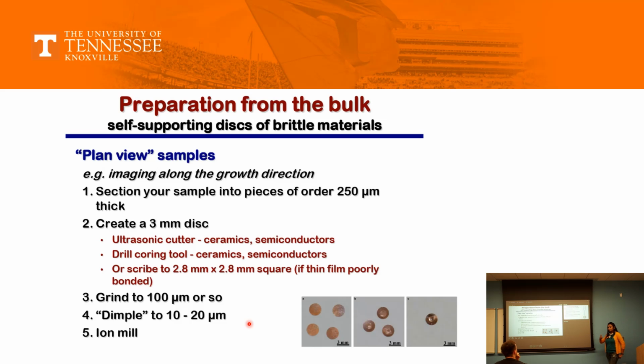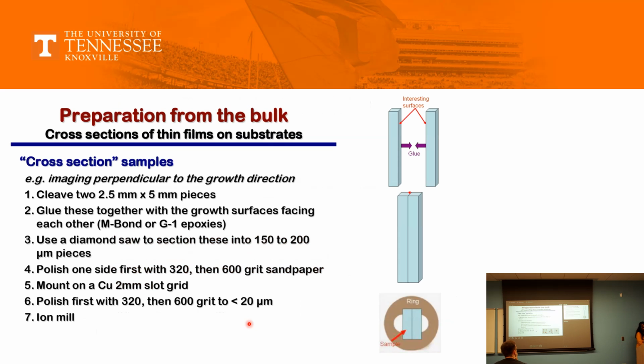When you go to FIB, you will see some samples will take you 8 hours to finish. Some of the intermetallics took that long because they were zirconium based. Depending upon the material, the FIB becomes efficient or inefficient. So now for ceramics, what do we do? All these things were developed initially and were really interesting. This is very simple: you develop it by polishing.